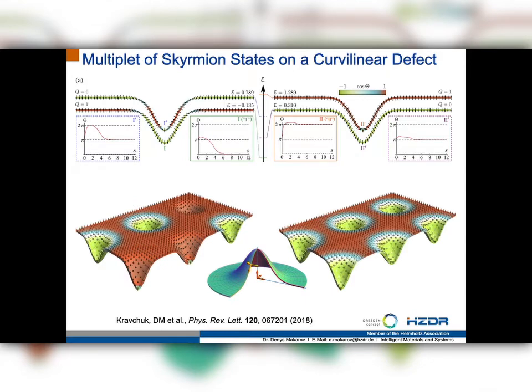And what is interesting about this curved system is that the energetics of these Skyrmion bubbles, which you can create in an array of these Gaussian bumps, is such that you will have a ground state which is actually the Skyrmion lattice, right? In this case, due to the interplay of geometrical curvature, you will have the possibility to tune the chiral interaction which comes from geometry and the anisotropic interaction which comes from geometry, in a way to make this the ground state. And now you can investigate the properties and parameters of this Skyrmion lattice in the ferromagnet, where the Skyrmion lattice is a ground state, which is not possible in extended thin films without corrugations, where the ground state is of course the homogeneous state, and Skyrmions are only excitations. So you have a very interesting playground for ferromagnets with such corrugations.